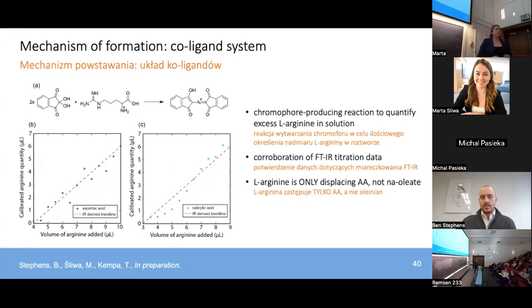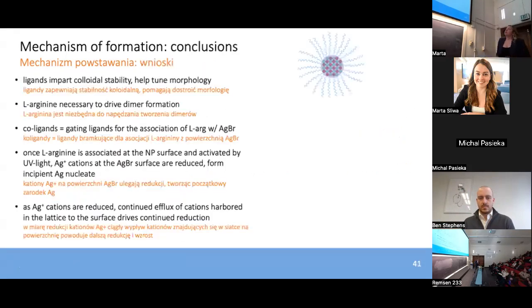So in other words, let's say we introduced a molar equivalent of 20 microliters of L-arginine into the solution. We know from the FTIR experiments, it only takes 4 microliters to displace the ascorbic acid. The absorbance of the L-arginine in that solution will correspond to 16 microliters, or 20 minus 4. Simple math there.